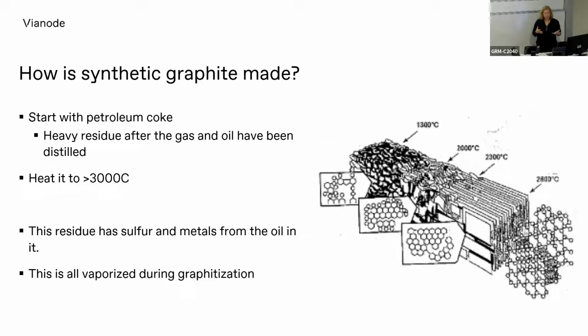Why do you have all these problems when you're making graphite? If we talk about how graphite is made, when we are making synthetic graphite, we start with petroleum coke. So it's a byproduct of the oil industry. After you have taken the oil out of the ground and you've taken off all of the gas and all of the diesel fuel and all of the heavy oils, you end up with this sticky, heavy residue at the bottom of the barrel. And that is what we use to make graphite.